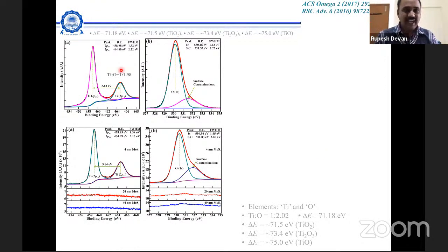XPS shows that initially the TiO2 remains in its proper format, 1:2. But when you form this 4 nanometer layer or 20 nanometer layer, then TiO2 may change, or MoS2 may change its own properties. Then MoS2 may convert into Mo oxide as well. The biggest challenge was how to identify that the 4 nanometer layer is on TiO2. We checked with XPS, because XPS gives information of a few nanometers, about 10 nanometer. So if you consider 10 nanometer, the upper 4 nanometer should be MoS2, and the bottom 6 nanometer should be TiO2. So you should get signal from both MoS2 and TiO2, and that's what happened here.